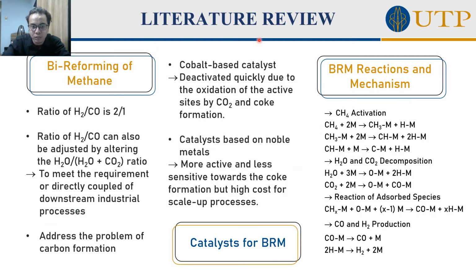Next is the literature review. Basically, the last two methods, steam and dry reforming, produce an H2 over CO ratio of 1:1. This is different from bi-reforming of methane, which produces an H2 over CO ratio of 2:1, which is better than the other two methods. This ratio can be adjusted by altering the water over water plus carbon dioxide ratio to meet the requirement or directly couple to downstream industrial processes. This can also address the problem of carbon formation.